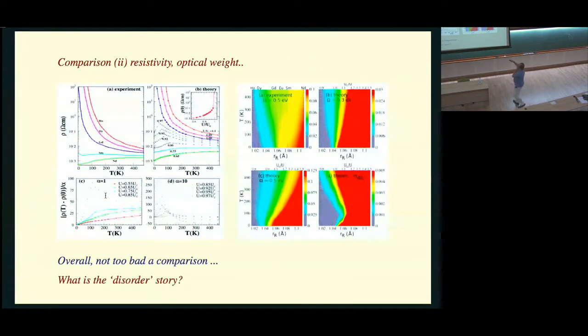Transport. So you saw these curves before, blowing up, going to a small value, if not 0, and an intermediate value here. These are color-coded to be sort of identical to each other. More insulating than in the experiment, but still blowing up, going to a finite value. These are all finite. In fact, you notice that if someone could make a crystal which had GdSm combinations in it, the trouble is it will introduce disorder in the problem. But if you could bandwidth tune, then you will get an unusual family of resistivity curves with increasing zero temperature values and a very odd looking temperature dependence. So these are consequences of your increasing spin and orbital disorder as you go from this end of the material to the upper end.